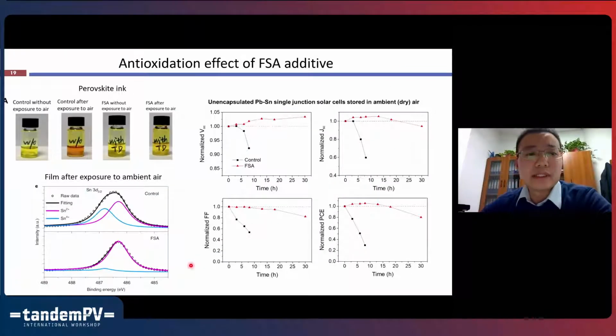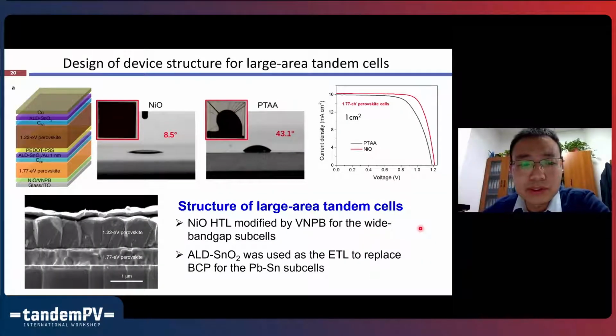And we also found that this molecule has the ability to suppress the oxidation of the film. For the unencapsulated single junction devices, when we stored them directly in ambient air, we found that with this molecule, they can stay in ambient air for almost 1 day without any performance degradation. But still, because it does not compactly cover the film surface, after 1 day the efficiency started to degrade quite quickly. So the next step is that we want to make larger area tandem devices.